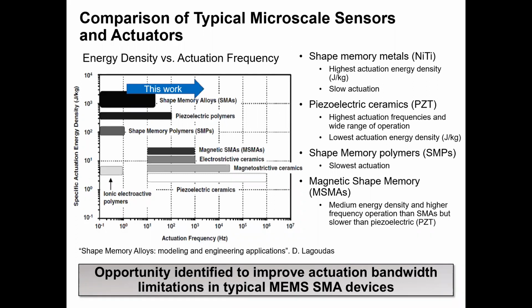So as shown in the figure of energy density versus actuation frequency, the NiTi-based SMA MEMS yield some of the highest energy densities at the MEMS scale. And this makes them attractive for applications requiring large force and large displacement. The room for SMA improvement, though, is in the actuation bandwidth, or in other words, the rate at which these SMAs can be cycled has historically been limited, based on the rate at which you can get the heat into or dissipated out of your actuator.